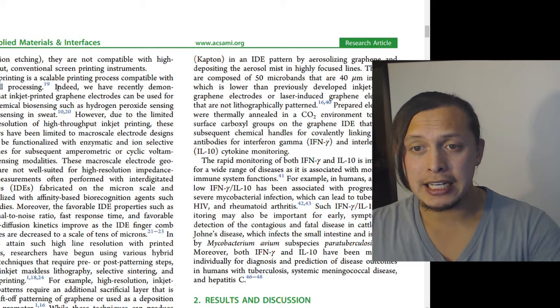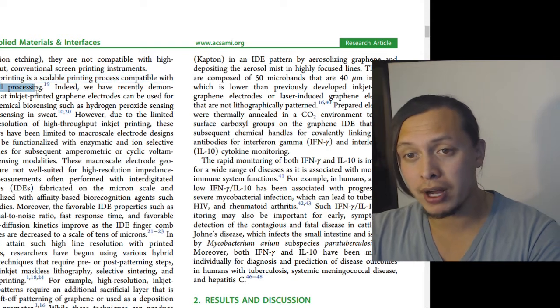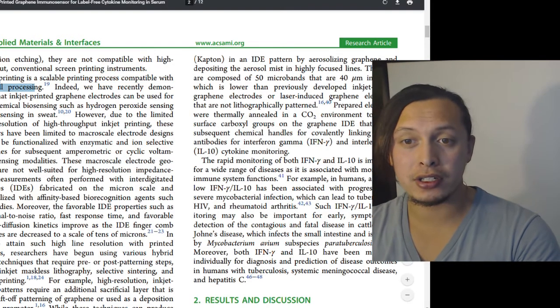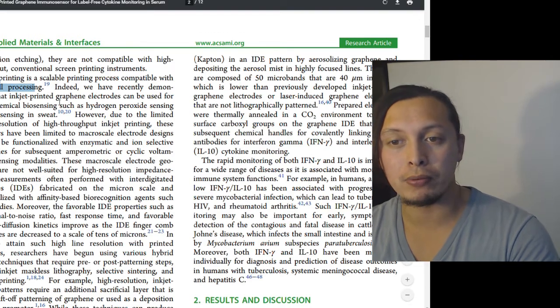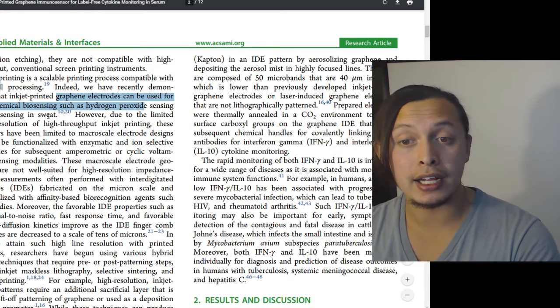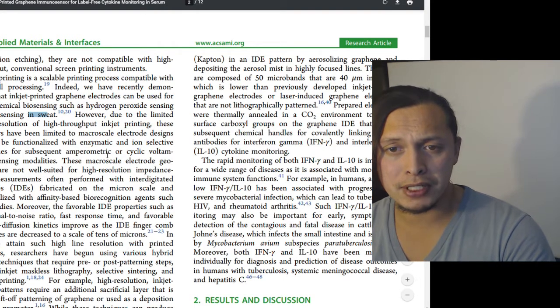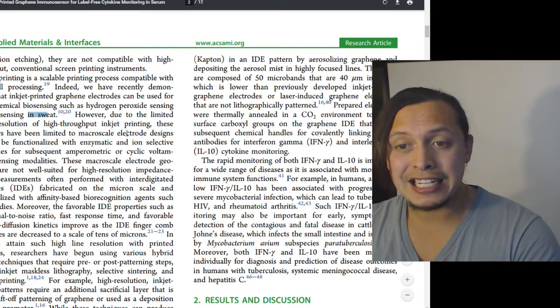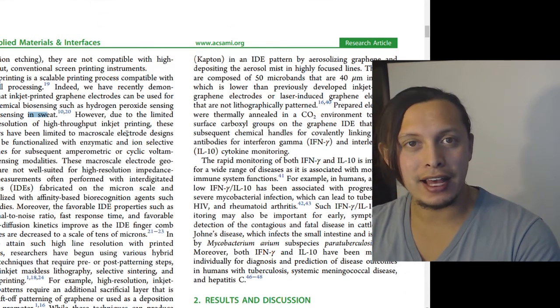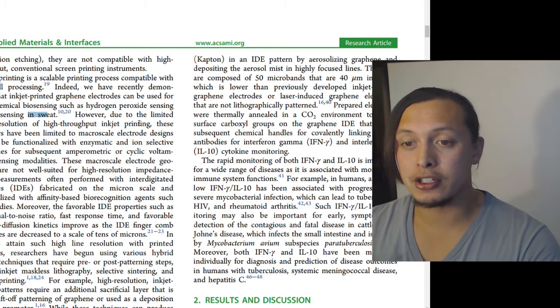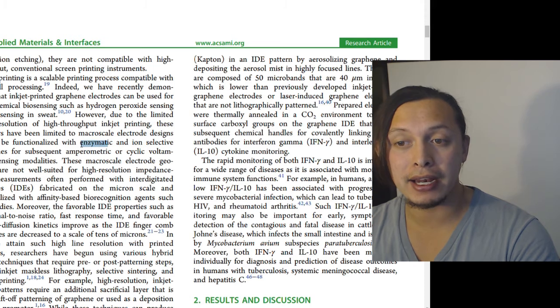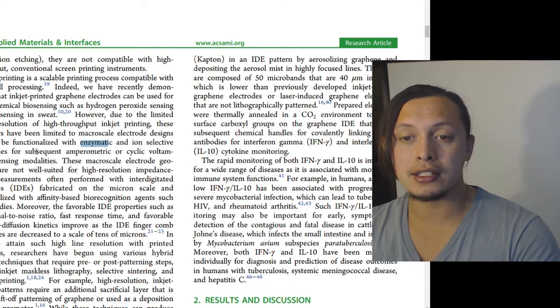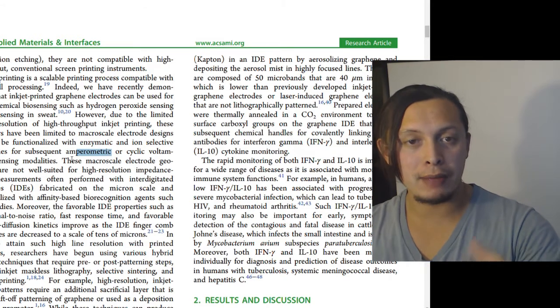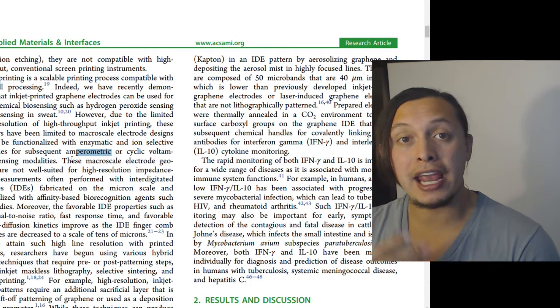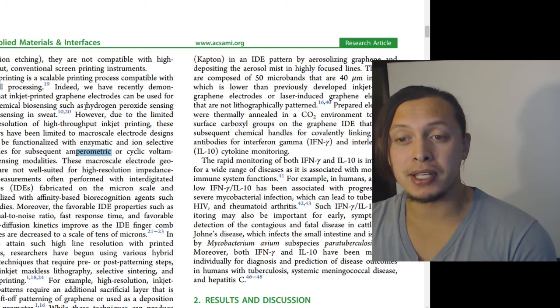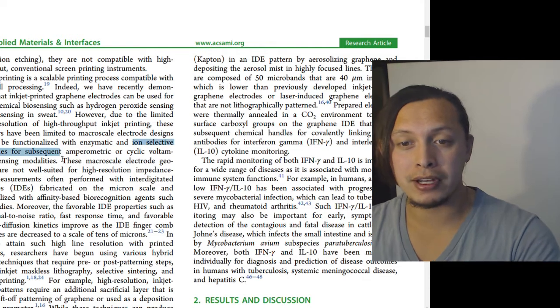So inkjet printing is a scalable printing process compatible with roll-to-roll processing. Indeed, we have recently demonstrated that inkjet printed graphene electrodes can be used for electrochemical biosensing, such as hydrogen peroxide sensing and ion sensing in sweat. However, due to the limited spatial resolution of high-throughput inkjet printing, these biosensors have been limited to macroscale electrode designs that can be functionalized with enzymatic and ion-selective membranes for subsequent amperometric, meaning measuring the current that is flowing through, or cyclic voltammetric sensing modalities.